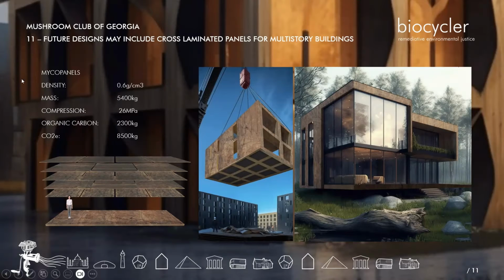So here are some of the factors again. So again, we're looking at about the same density. So 0.6 grams per cubic centimeter, the mass very high because we're talking about big materials. But we're moving closer to the compression strengths that we're getting here in Cleveland with the smaller presses, but these would be much, much bigger presses, but have a lot of force behind them to create the 26 megapascals, which again is strong for concrete even.